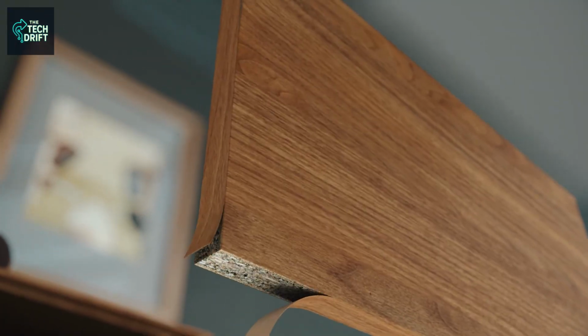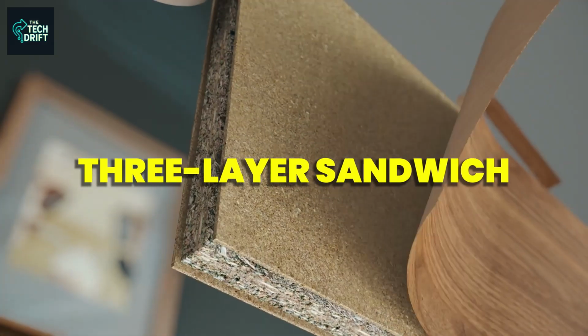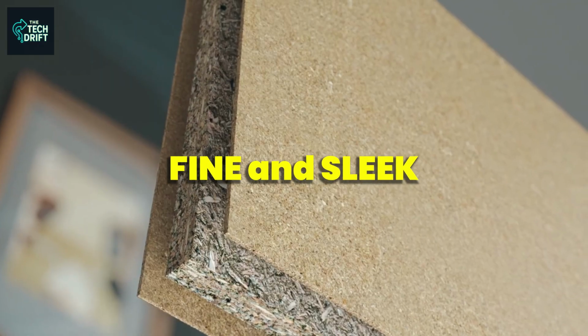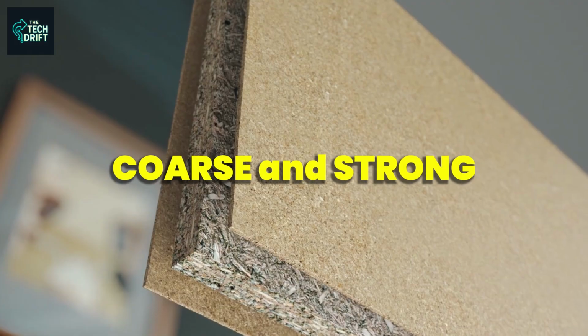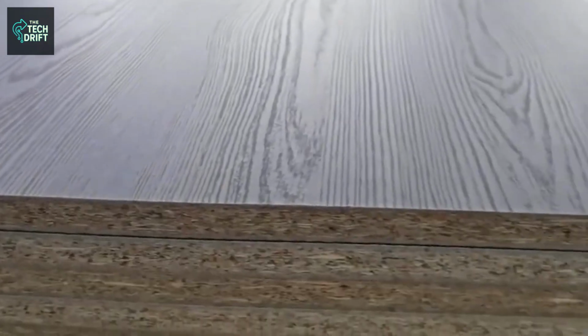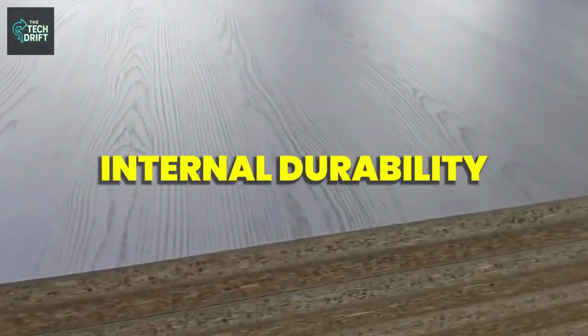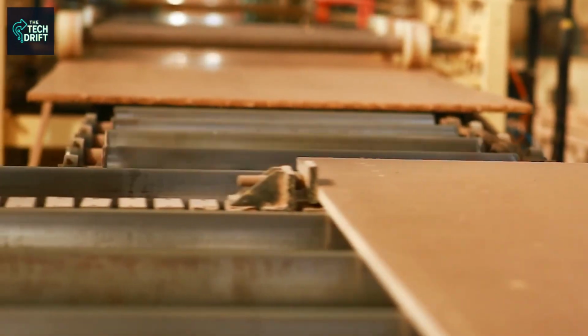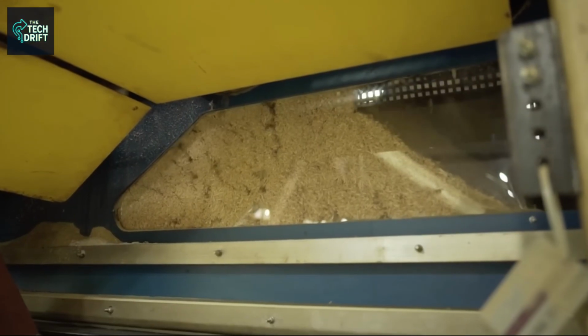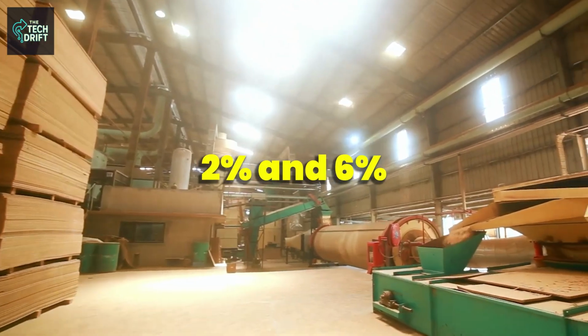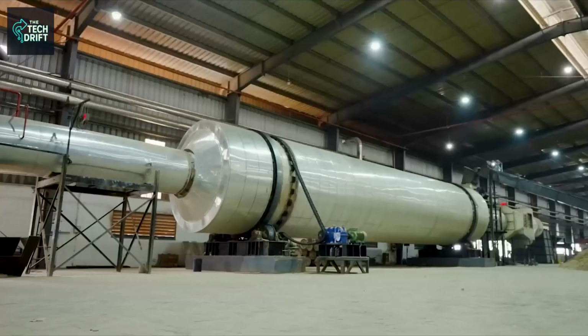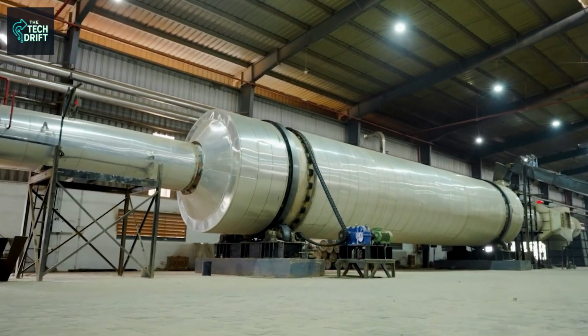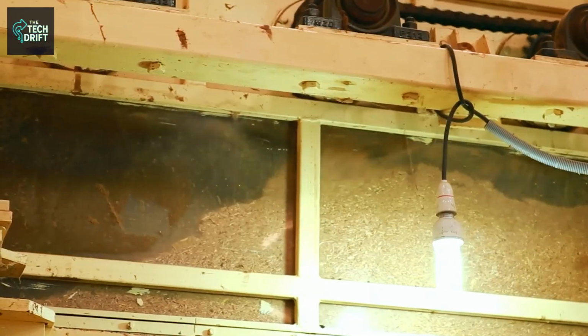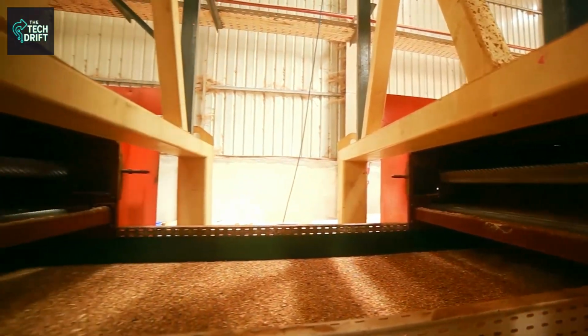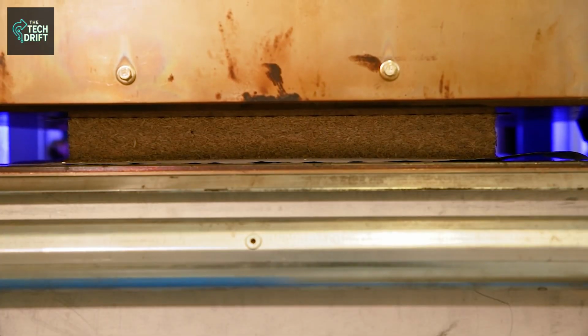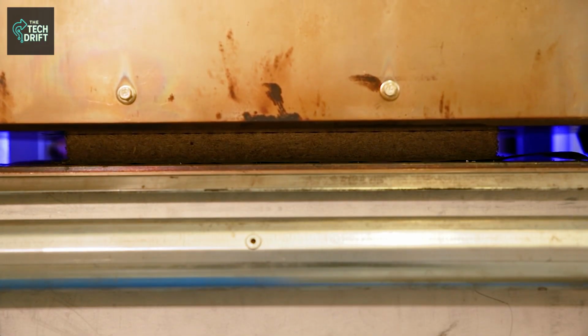This careful layering forms what manufacturers call the three-layer sandwich. The outer layers are fine and sleek, while the middle one is coarse and strong, creating a balance between surface beauty and internal durability. To make sure these layers bond perfectly later, the flakes must be dried to a critical moisture level between 2 and 6%. Drying happens in huge rotating drum dryers where hot air flows through continuously. If the flakes are too dry, the resin won't bond evenly, and if too wet, trapped steam can cause the board to rupture from within during pressing.